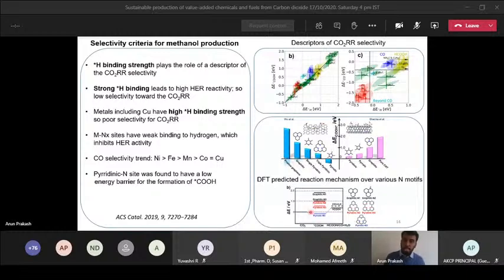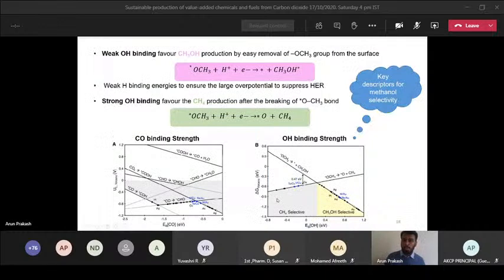And weak OH binding, similar to hydrogen binding and also CO binding, OH binding strength also determines the methanol selectivity. Depending on the OH binding strength, you can either produce methanol or methane. And CO binding strength also determines your product selectivity. For instance, if the hydroxyl binding strength is a negative value, your CO2 will be reduced preferably to methane instead of methanol. If you can tune the hydroxyl binding strength to a more positive value like 0.4 or 0.8, then you can get methanol instead of methane. So this is how you can tune your selectivity.